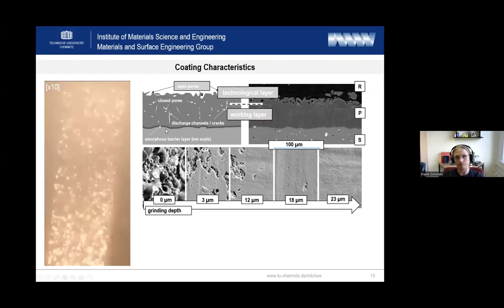And over this barrier layer, we find an area of very dense oxide material, the so-called working layer, which offers the most real protection. And over the working layer, we find a region with a higher porosity, the so-called technological layer, which you can use, for example, to apply some color or maybe Teflon or other additives. This technological layer offers a good substrate bonding to further resin or color or whatever you want to apply on it. And inside the dense oxide structure, you find some remaining porosity, some discharge channels and cracks, and also some closed pores.